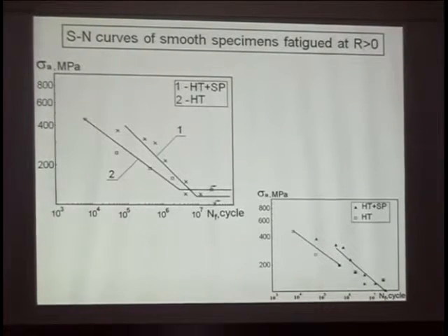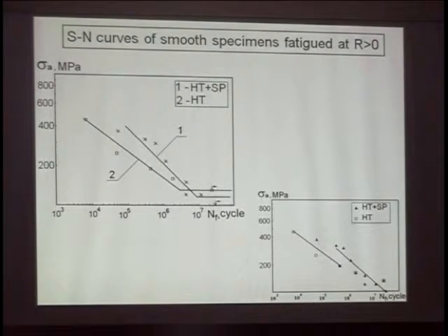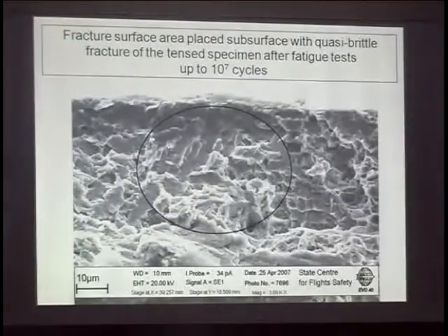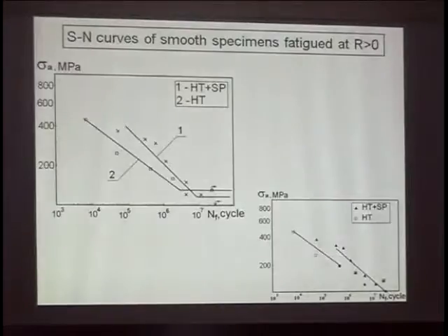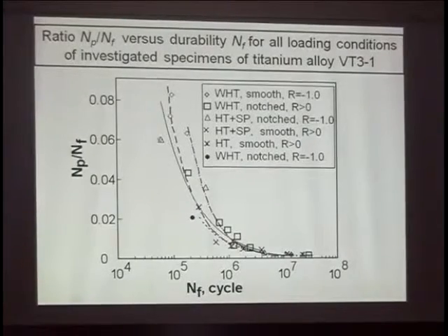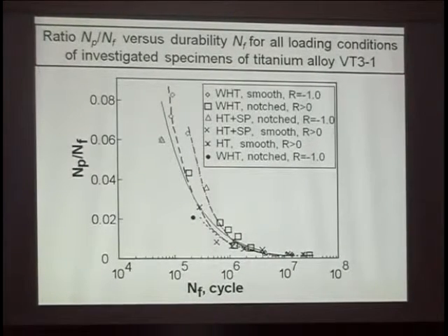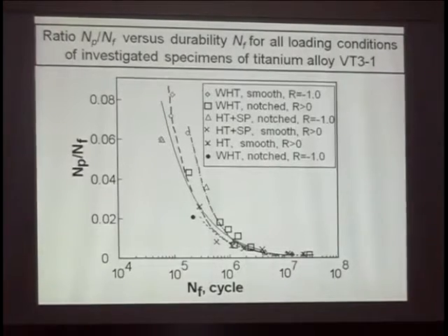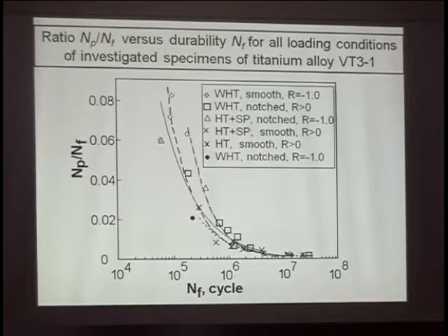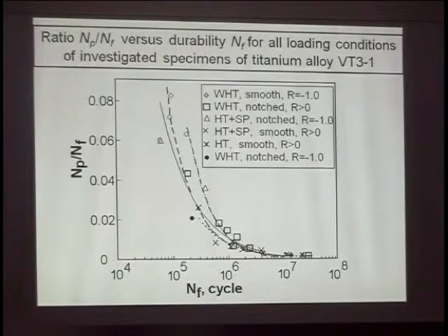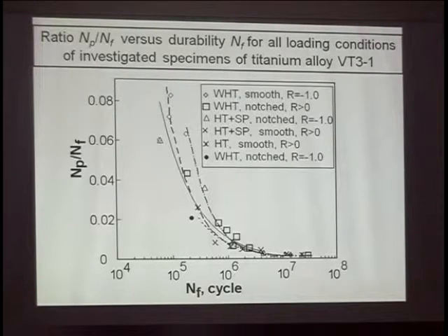As you have shown a very interesting diagram where you plotted NP over NF, the propagation life over total life, as a function of the total life, it looks like the propagation life here is very small in comparison to the total one. So what is the remaining part? You would call it initiation? What's going on before the crack starts propagating? It depends on the stress level, because at a high stress level it may be 30% or maybe more, but for lower it may be 10% or less.